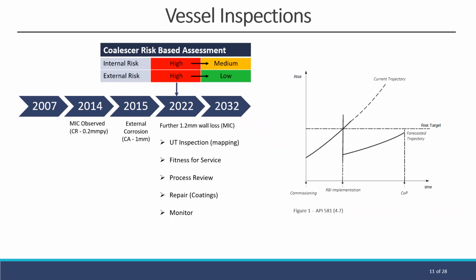Vessel inspections is another high risk area. So what we recommend, we have a lot of vessels that have limited history. So what we recommend is a risk-based inspection implementation to be able to determine and focus inspection on the high-risk areas initially. An example of this is the coalescer, where both internal and external risk and threats are simultaneously happening, with MIC noted in 2014, external corrosion the year later with a 1 mm corrosion allowance, and bringing up to speed to date, we've now had a further 1.2 mm wall loss.